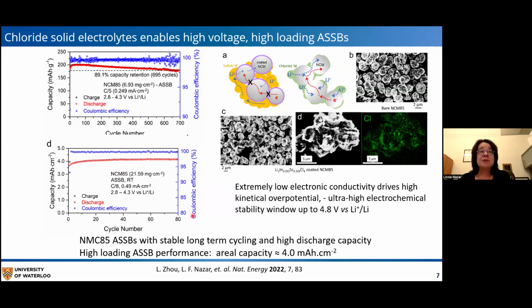And as I said, this is by virtue of its very low electronic conductivity, and this drives this high kinetic overpotential. And we've been able to cycle these cells for 100 cycles or so, even up to 4.8 volts, which far exceeds the thermodynamic redox oxidation potential, which is on the order of 4.2 volts.